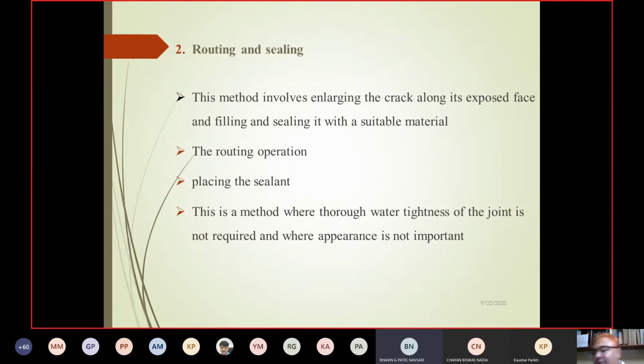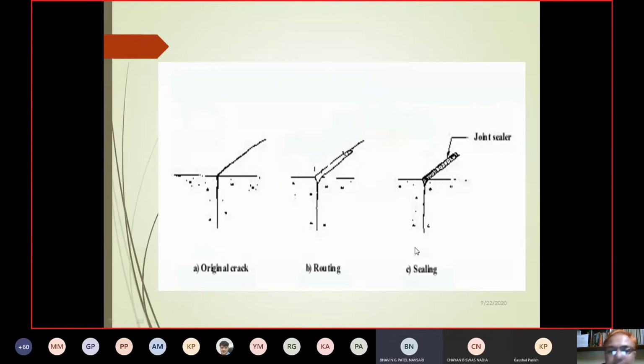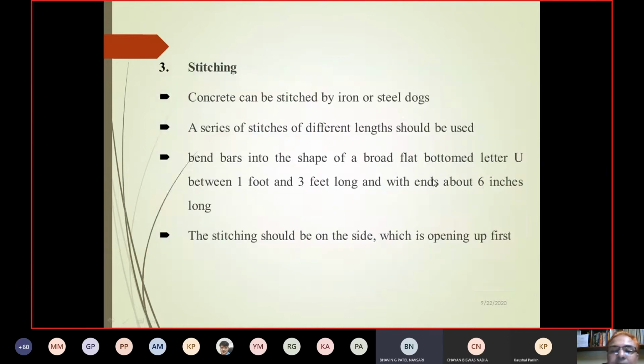Then routing and sealing. First, we have to route the particular crack. This method involves enlarging the crack, opening it V groove by V groove, filling and sealing with a suitable material. Now, routing operation, placing the sealant. This is a method used where water tightness of the joint is not required and appearance is not important. Here is the original crack, routing by V groove, and filling the material.